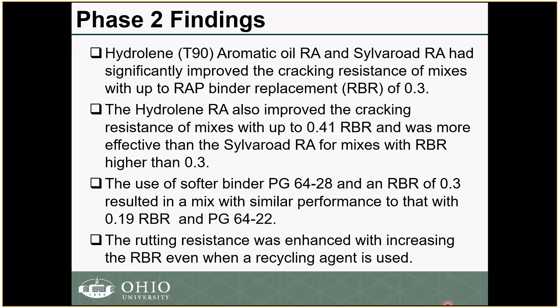What we have seen is the Hydrolene and the Sylvaroad basically have improved significantly the cracking potential for phase 2 and for the test sections, the cracking resistance of the mixes when using a RAP binder replacement of 0.3. We can see that the Hydrolene had a much better improvement when the RBR was 0.41 as compared to the Sylvaroad. But beyond that 0.41, that recycling agent improvement was not significant to overcome the increase in the RAP percentage or to overcome the effect of the RAP on the mixture fatigue cracking resistance.